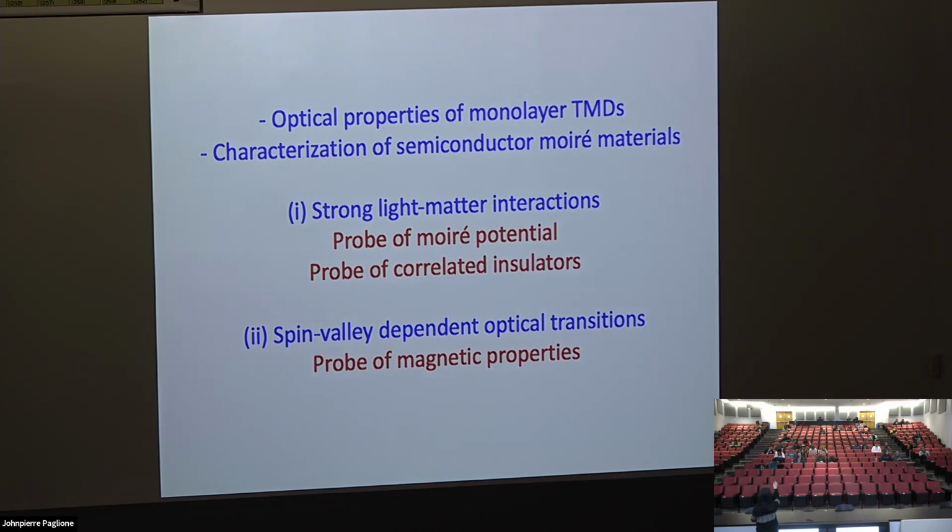So since I talk about filling equal to 1, then let's look at the first Moiré mini band. So this will just be like the top of the valence band I showed you, right? It's cutting a tiny bit of that. And the Fermi level goes through the middle of that gap. Okay. And if you have strong interaction, that band is split into the upper and the lower Hubbard band. So that's kind of the valence band.